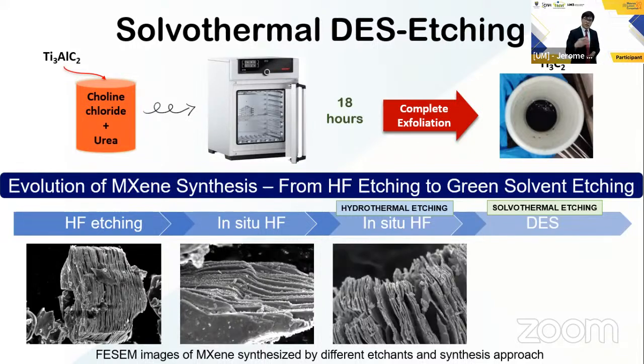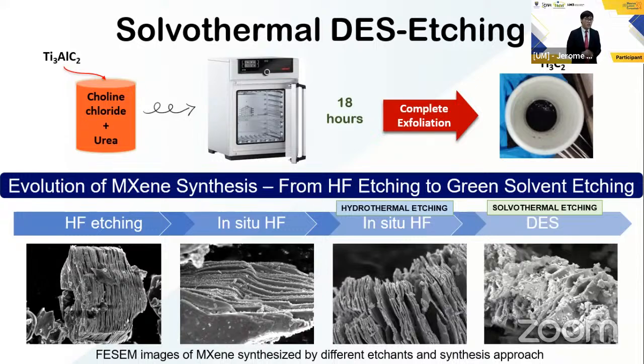And then hydrothermal assisted etching and solvothermal assisted etching come along. These etchings are better approaches to make MXenes because they actually produce MXenes with better quality than the conventional ones. The MXene flakes are larger, they are of higher quality, they are less defective because these etchants are less harsh to the material as well. And these factors are paramount to the electrochemical performance of these MXenes. And more importantly, they save time and are greener than these conventional methods.